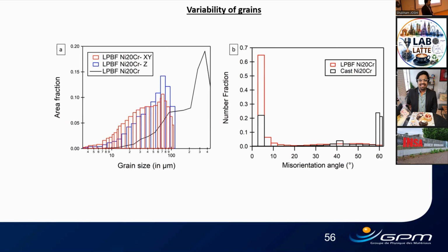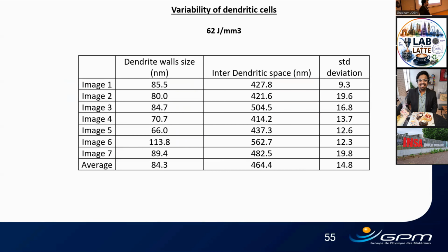Yes. So you show that there is a high contribution of the solidification cells, right? So this is quite convincing. You're talking about the size of the dendrites. I was wondering if there could also be, maybe at the second order, an effect of the thickness of the walls. And there's a lot of things in your walls, the dislocations, the precipitates, so you talked a little bit about them in the prospects. Do you also have some heterogeneities in the chemistry between the walls and the inside of the dendrites, or is it homogeneous?